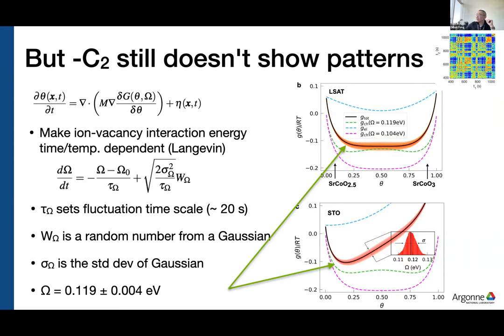omega that was time dependent. So that's the ion vacancy interaction term. And so they decided to follow this Langevin equation, which I'm showing right here in the middle for d omega dt. And you can see that they've now made it time dependent, and through some of these parameters, they could make it temperature dependent. So tau sub omega sets the fluctuation time scale, and they arbitrarily played with it, and they could get it to match what we see with 20 seconds.